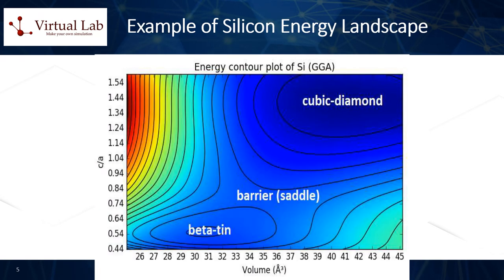The image displayed here shows an example of the ground state energy landscape surface for single crystal silicon, computed with ab initio density functional theory methods. The global energy minimum at ambient conditions, corresponding to the equilibrium cubic diamond phase of silicon, is clearly visible at the top right corner of this projection. The beta-tin phase, which becomes the most stable at higher pressures at around 120 kBar, also appears as a metastable phase within such ambient conditions energy plot, in the form of a local energy minimum.